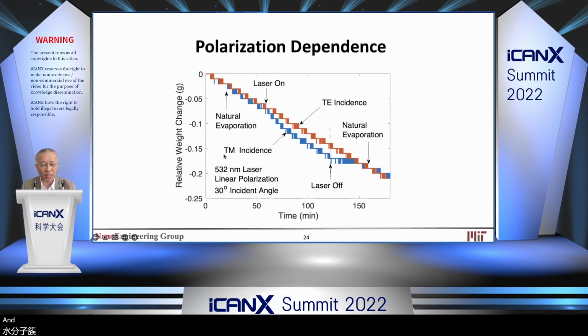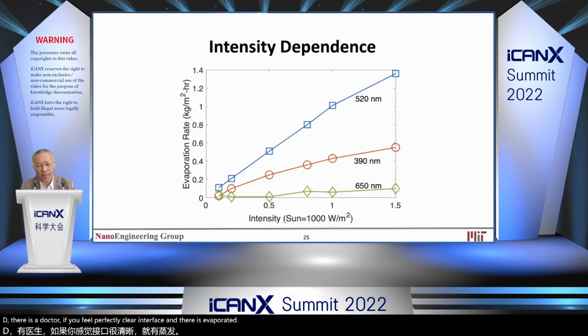And this is another check where we use polarized light, because we need the electric field perpendicular to the surface. If you have a transverse electric field incident, this is using a laser, it doesn't happen. So for TE, you can see when the laser is on, there's no reduction in evaporation. But if you have a transverse magnetic incident, there is an electric field perpendicular to the interface, and there is evaporation. And we also saw the intensity dependence once you go to higher intensity above 1 sun.